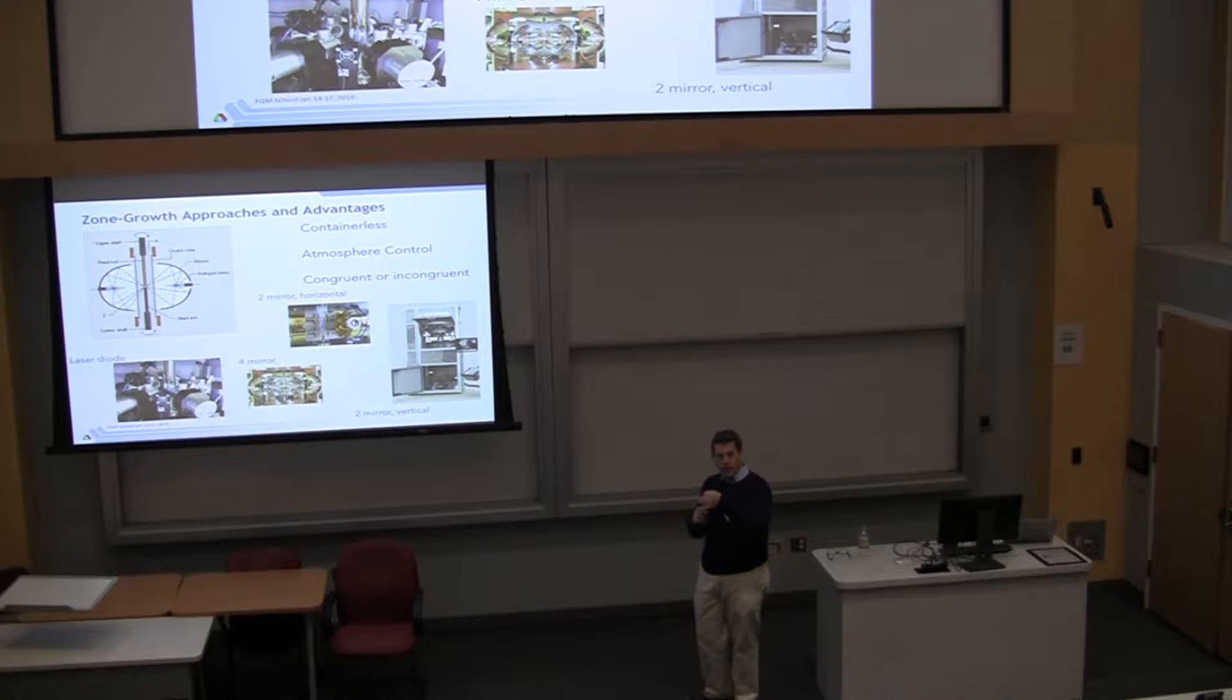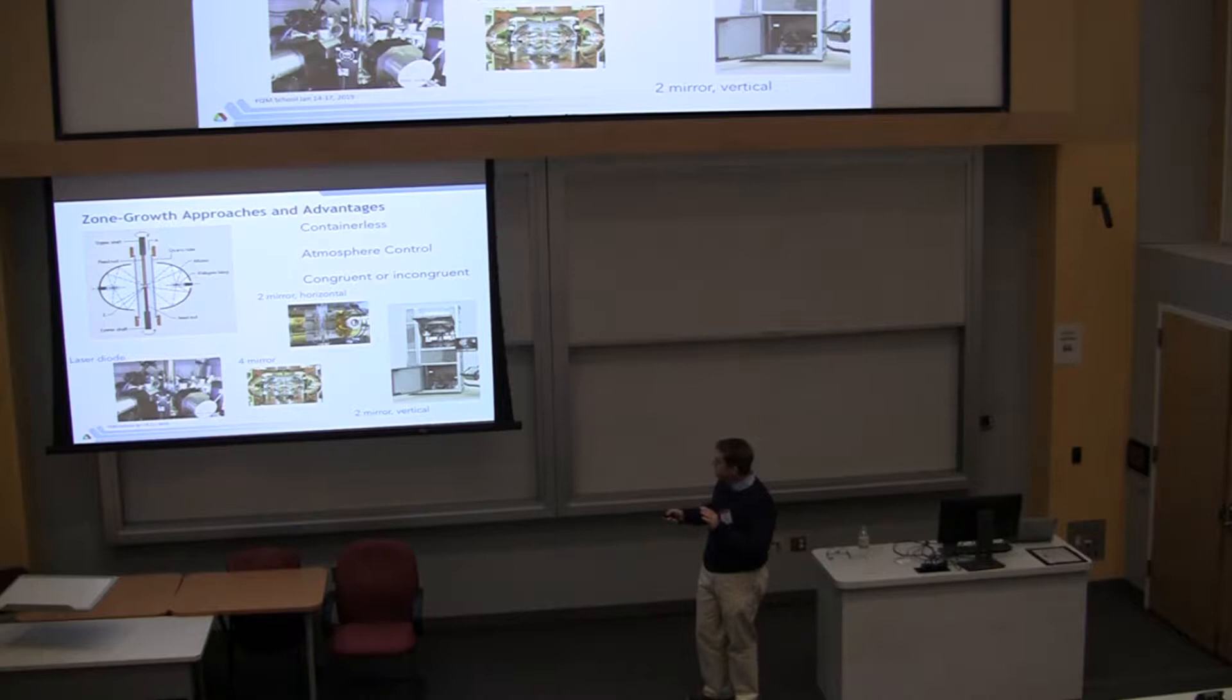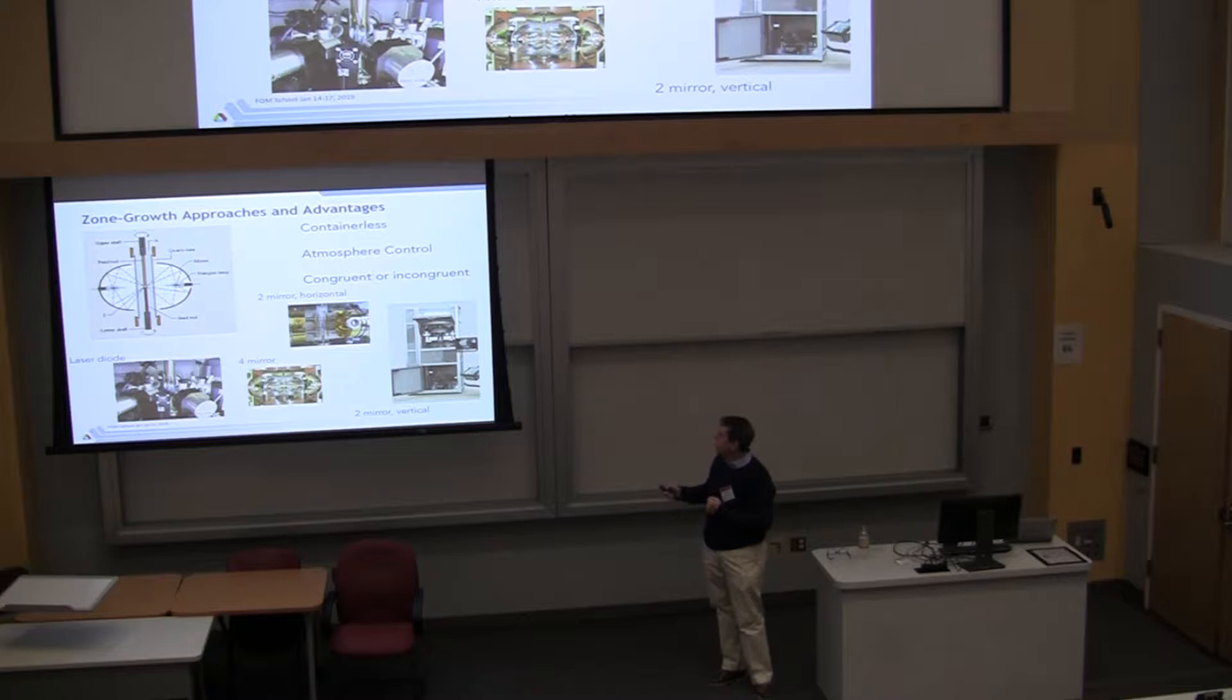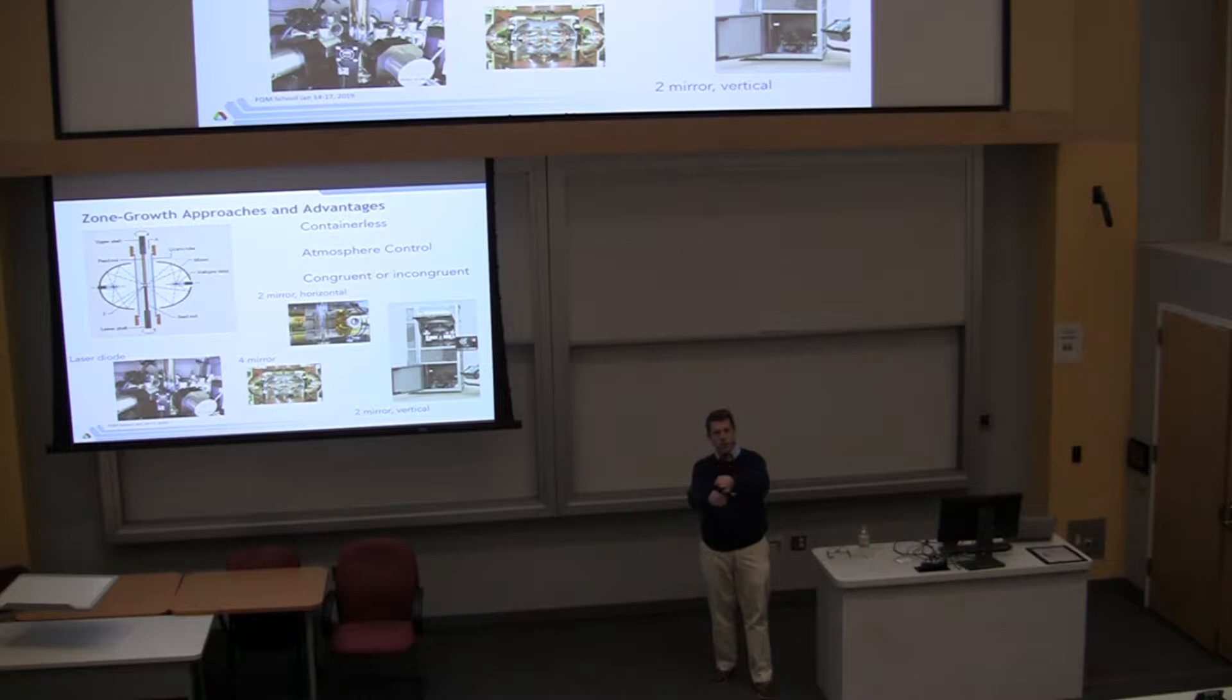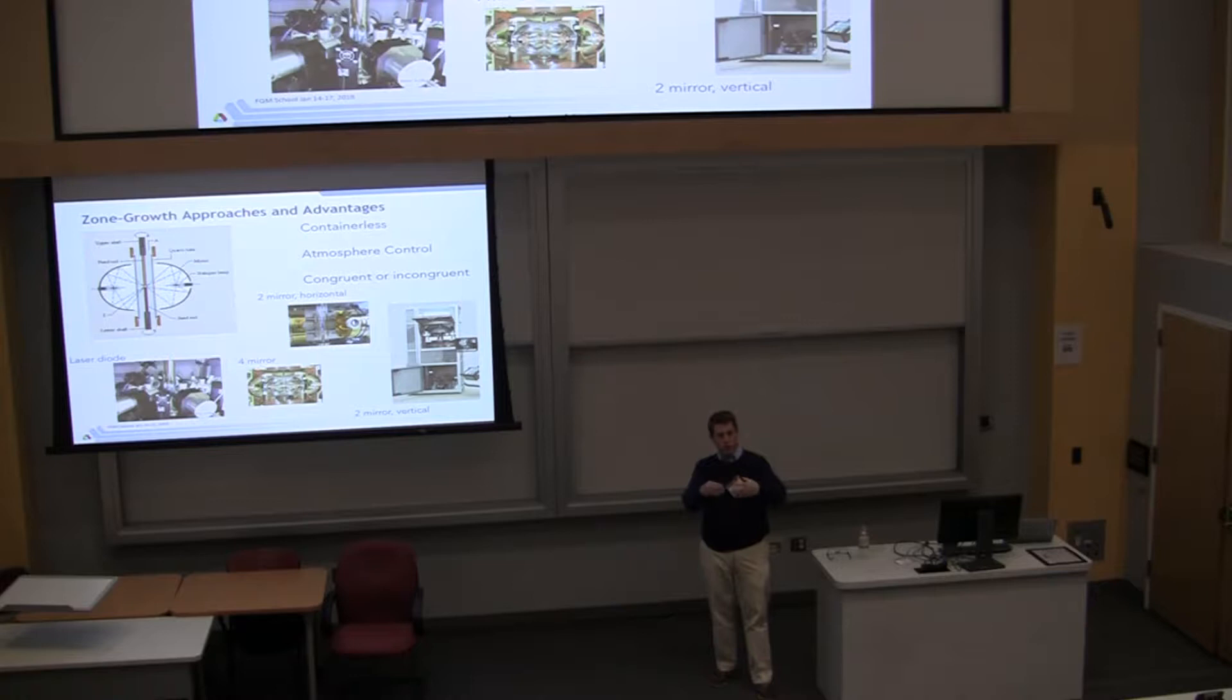Now it's gotten better with places like the SNS, but still they like to have these big crystals. And so you don't grow a big crystal like this typically by vapor transport, or you don't grow it by fluxes. You get small crystals that way. But this zone refining technique, which was actually developed in the 50s at Bell Labs as a way of purifying silicon, has been adapted by the materials physics community to grow crystals of complex materials.